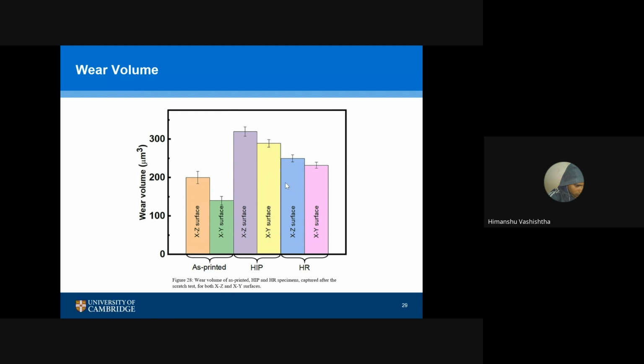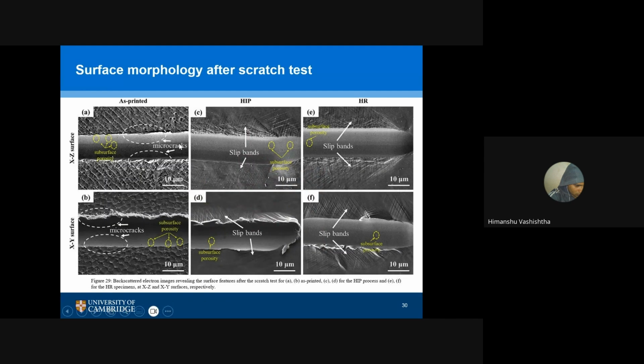To measure the wear volumes, we have used a nano indenter. I'll show you in the next slides what we did. We use a nano indenter and mark a scratch. I believe many of you are working with wear and similar things, so that's a pretty good practice to measure the volume. The area under the curve multiplied by the length gives you the wear area, and from that the wear volumes have been calculated.